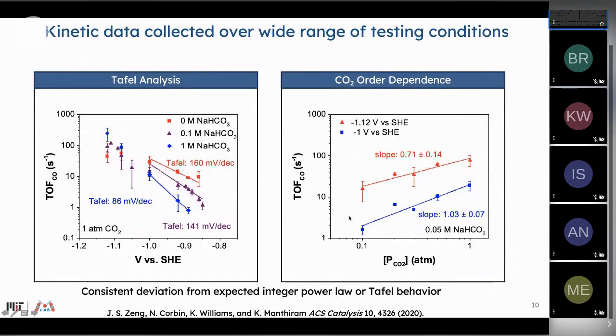We can also look at the Tafel slope under a more diverse set of conditions. What I showed before was a very narrow range of bicarbonate concentrations. We can instead remove bicarbonate entirely or go to a much higher concentration of bicarbonate, and we see different Tafel slopes. It turns out that even something as apparently simple as a Tafel slope depends on bicarbonate concentration. We can go anywhere from 86 millivolts per decade to 160 millivolts per decade.